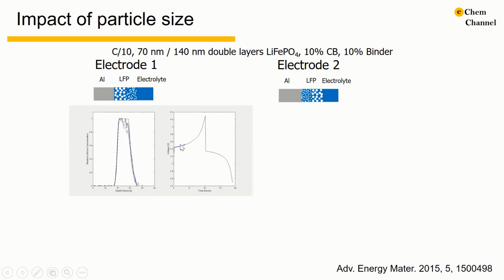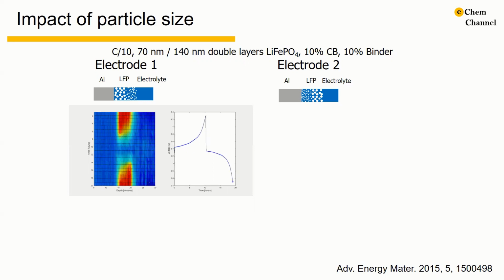The data is collected again, and the final pattern is given here. It is clear that the larger particle close to the aluminum current collector loses lithium slower when voltage increases, and gains lithium also slower when voltage decreases again. It means that larger particles near the current collectors charge more slowly than the smaller particles close to the electrolyte.